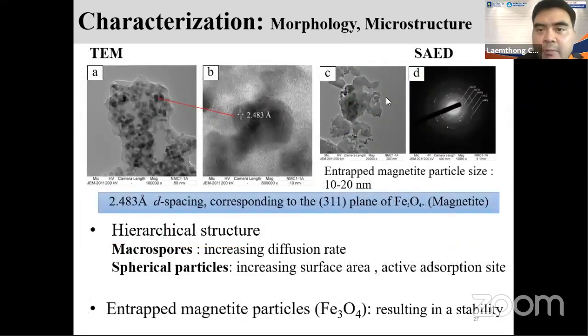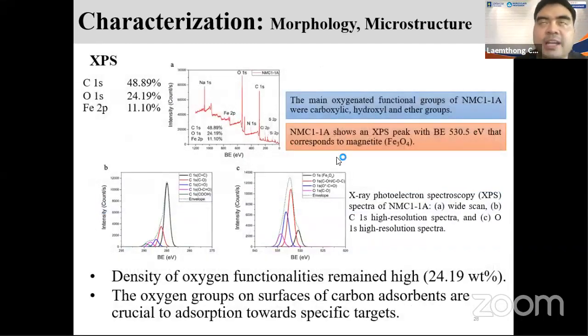Yeah, this is what I want to show. From another technique like TEM, you can see that we have the iron oxide, Fe3O4, trapped inside the carbon matrix, and we determined using the EDX and confirmed that we have the iron oxide. And beyond that, we talk about the chemistry of this. So we still have a lot of oxygen.